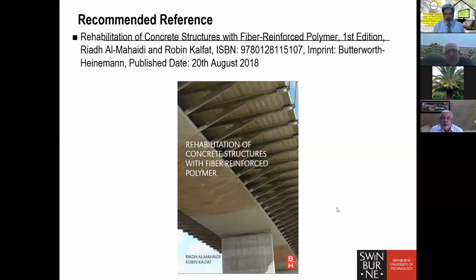Temperature variations is a problem. There is something called the glass transition temperature of the epoxy. When the epoxy cures and hardens, it goes into a solid state, like glass. But if you expose it to high temperatures, it starts to melt. So it transforms from the solid state to the fluid state. And usually these epoxies that we use have a glass transition temperature between 65 and 80 degrees.